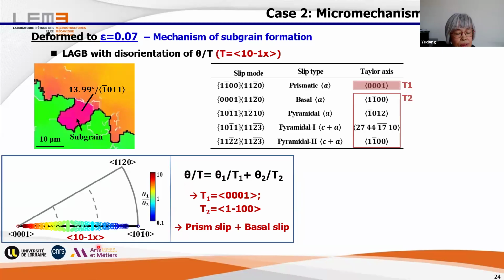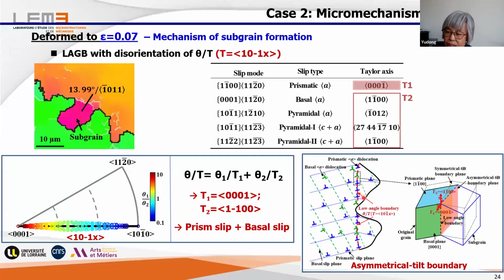And so you see, if we plot the axis, it is distributed along this orientation line. So you see it goes from a pure prismatic slip to a pure basal slip. With this, we could further analyze what happened. At the beginning, we have the activation of the prismatic slip. And then we have the activation of the basal slip. And the boundary area will absorb this basal slip inside and then make orientation evolution of these two parts. And so it's illustrated here.